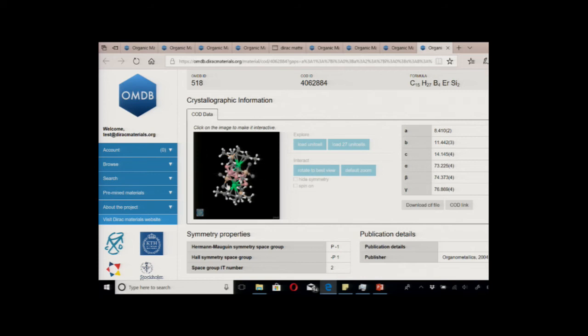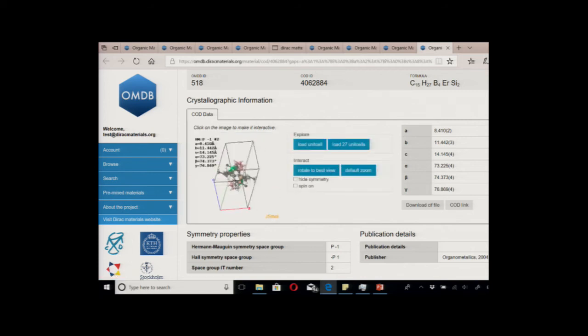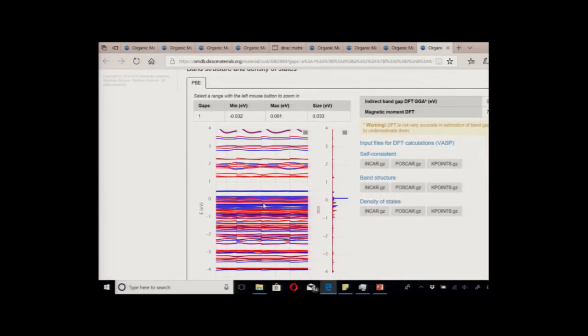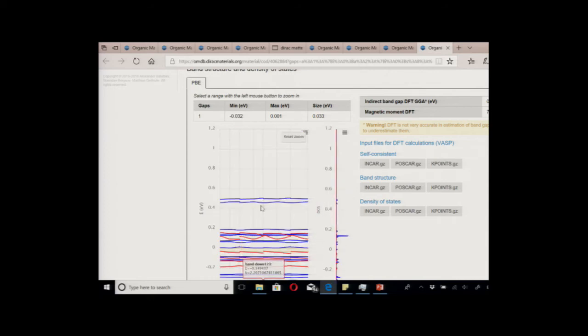This is a very complicated molecule, as you can see from here. And this one happened to be ferromagnetic. The color here means spin up and spin down, and we find out that this material is a ferromagnet. Let me see if I can zoom in. Right, so this hatched light yellow, beige region here is exactly this 0.1 electron volt, or whatever the request was. It's the small gap near the chemical potential, but you can see there are a lot of flat bands at this place, near 0.